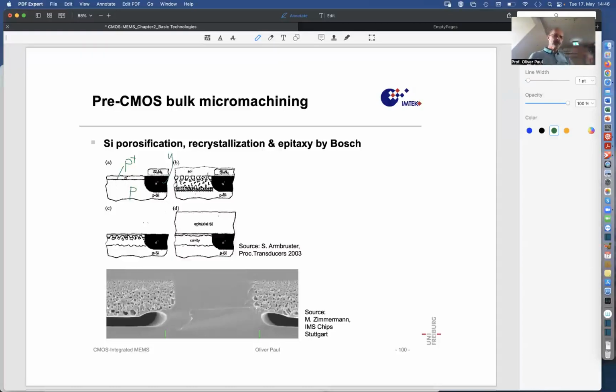And then, of course, one takes out the wafer, one cleans it, one dries it, and then one puts it into an epitaxial reactor, this epi reactor. So silicon is raining down on this surface that is still a rough surface. I mean, there's silicon with many pores. Silicon deposits on that silicon, finally closes everything. So the surface is becoming closed, and then more epitaxial silicon grows to a thickness of a few micrometers.